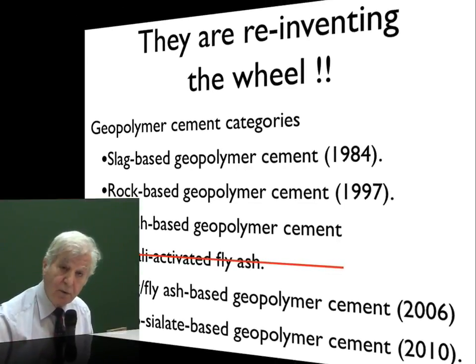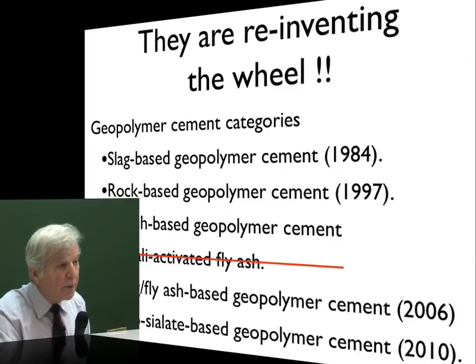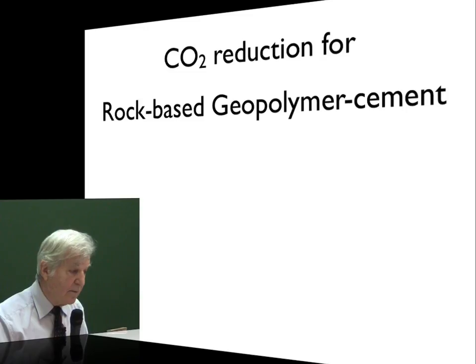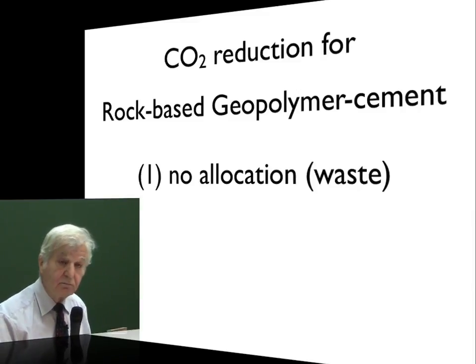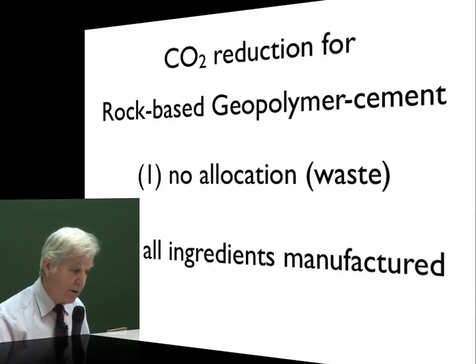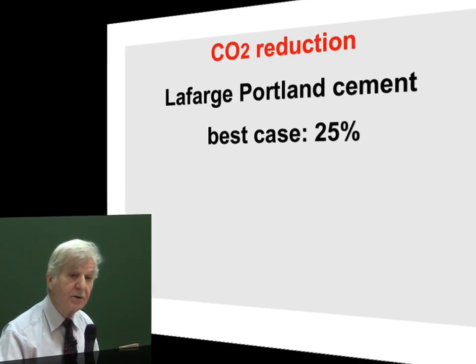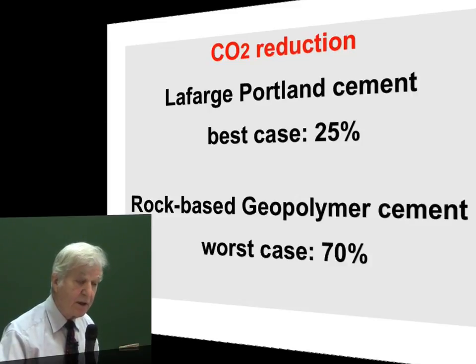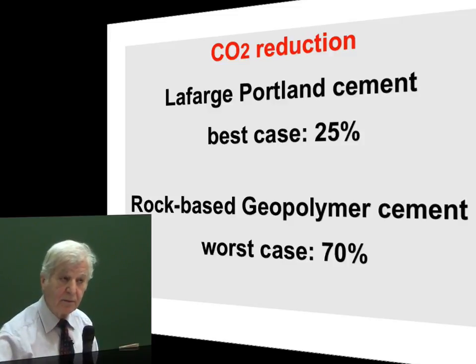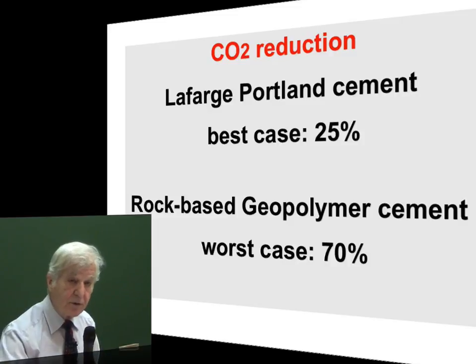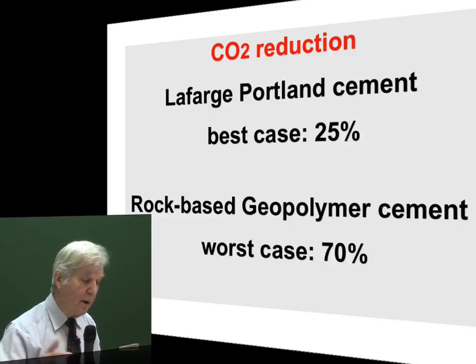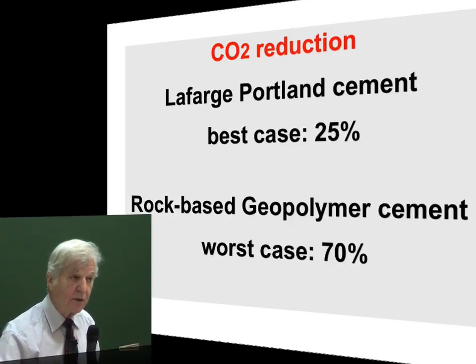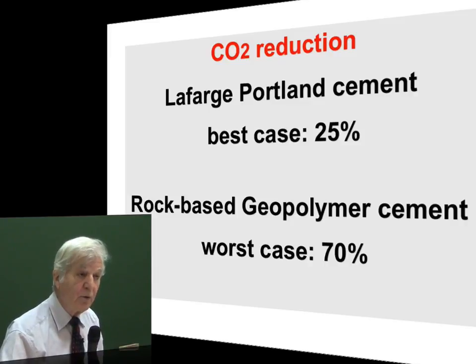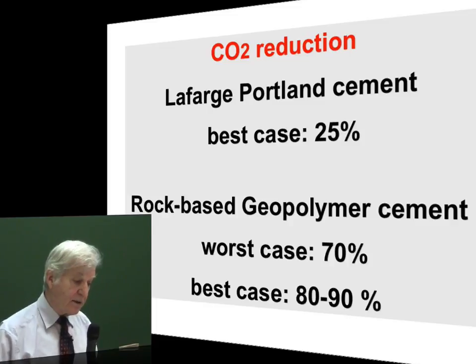So all this information is available. These people are aware of that. They are attending the geopolymer conferences. They are coming to the Geopolymer Camp and publish misinformation. If we compare the CO2 reduction between what we have and what Lafarge has, best case for Lafarge, 25% reduction, this is what they are claiming. Rock-based geopolymer cement, worst case, if we must manufacture everything, 70%. First, why? Because our temperatures are lower, because a lot of things, and of course I don't take into calculation the equipment that is totally different, that is cheaper, and in best case 80 to 90%.